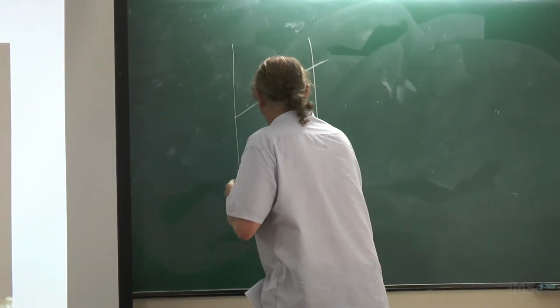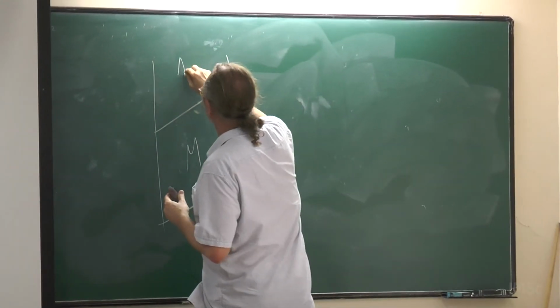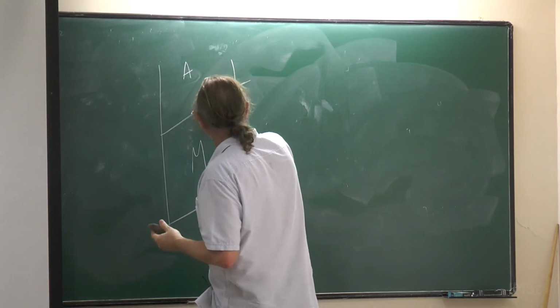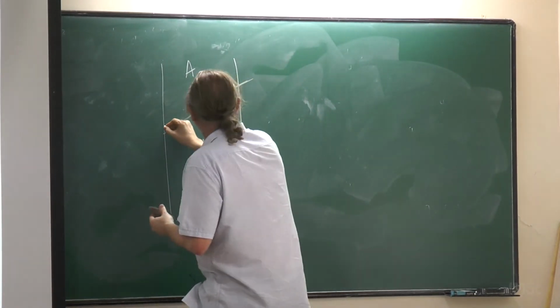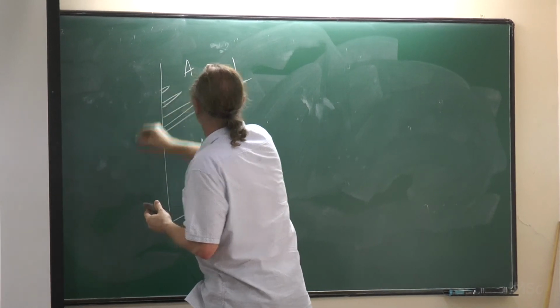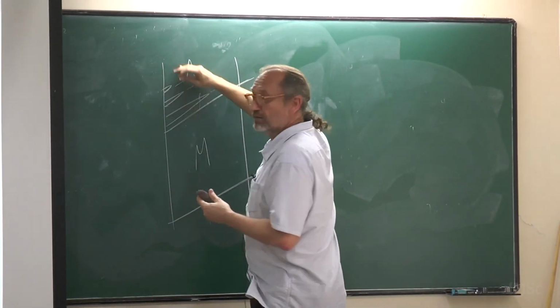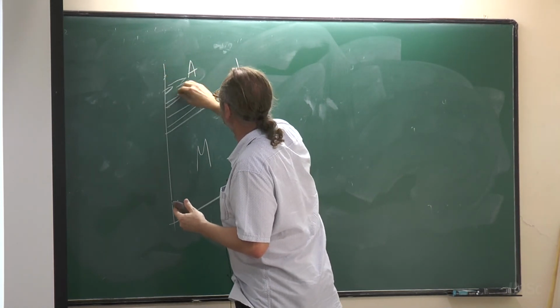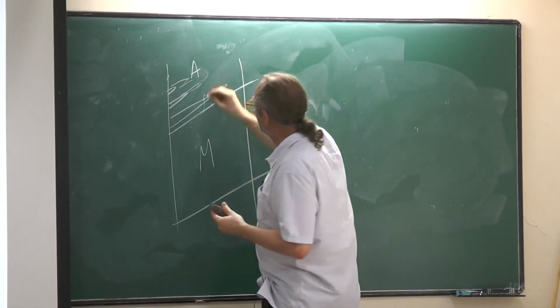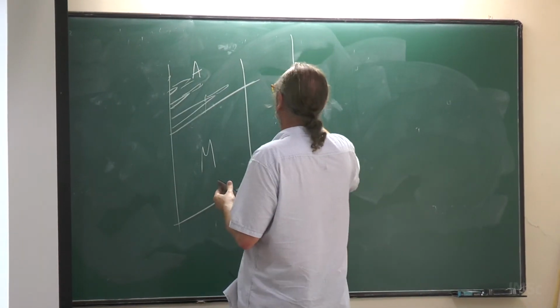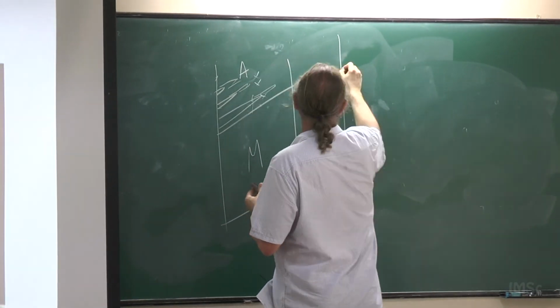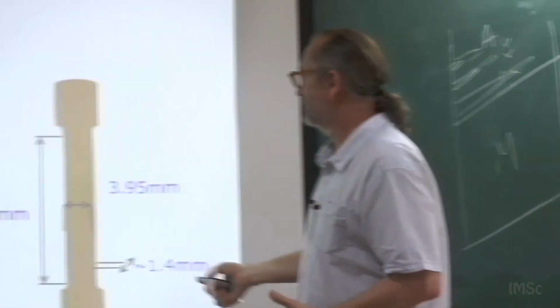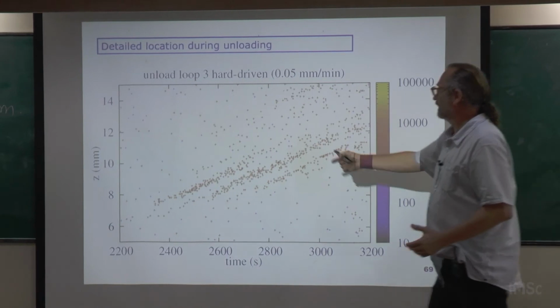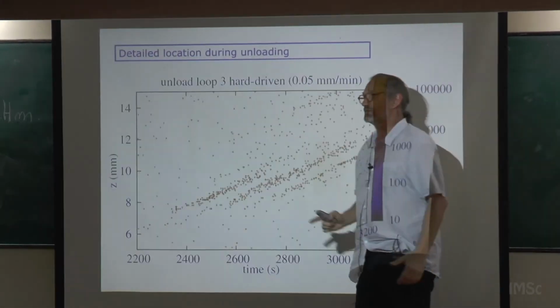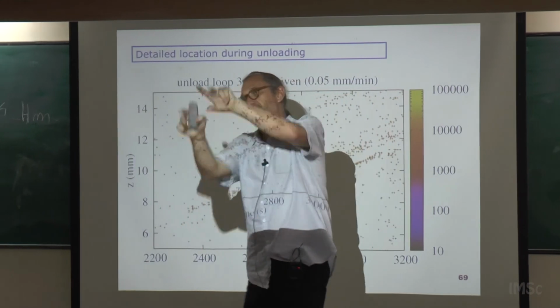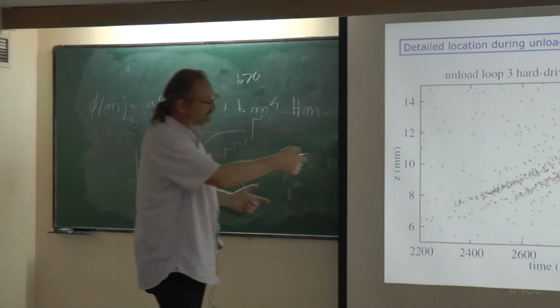So this is the martensite, and this is the austenite. Well, when you unload, it does not advance like that. It advances creating some needles like this that advance and fill. And then it creates a new one here. This grows like that. And when you project that into the Z direction, you see activity here, here, and here. So at the same time, you see activity in three places. These are the needle tips that clack, clack, clack advance. And we can measure the distance between the tips, etc.